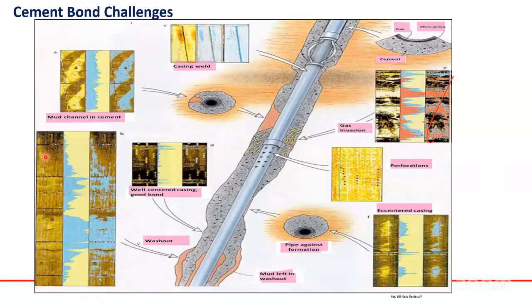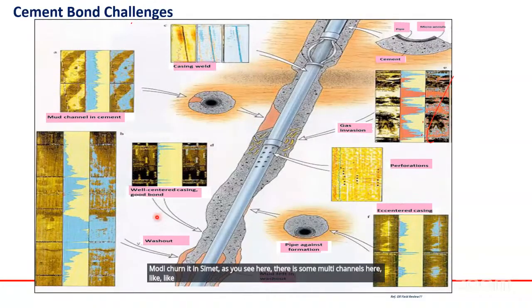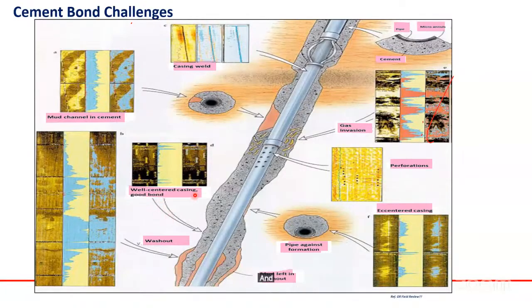What are the cement bond challenges? As you see here, we may have casing weld. It will appear in the casing in log interpretation. Muddy channel in cement. As you see here, there are some muddy channels, like these ones. And well-centered casing, good bond. Okay, as you see here, this is well-centered. The cement around the casing is good and centered, and we have a good cement, right? Washout in the formation itself. So you may have some mud on it. It will appear in the interpretation.